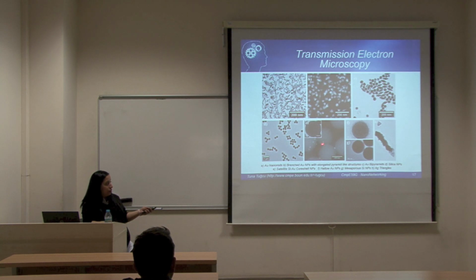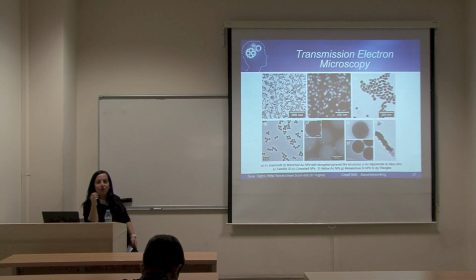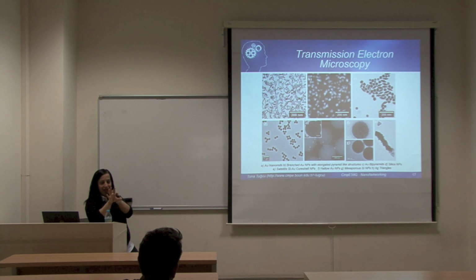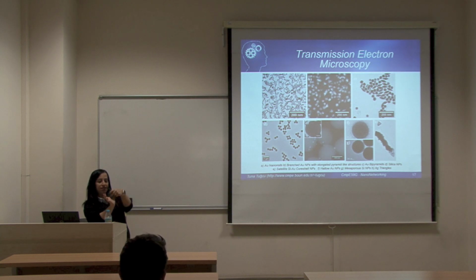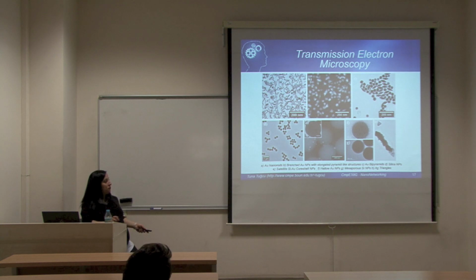Another thing you can obtain is hollow silica structures. This is a hollow particle. It's a mesoporous particle. Meaning that I just melt the gold outside, and I have the silica nanoparticles, which are mesoporous. See, there are cavities in them, and I can use this to attach my biomolecule for cancer detection, because you have an active surface and a lot of surface area created by the cavities. So the biomolecule which is used for biorecognition can just attach in these cavities.